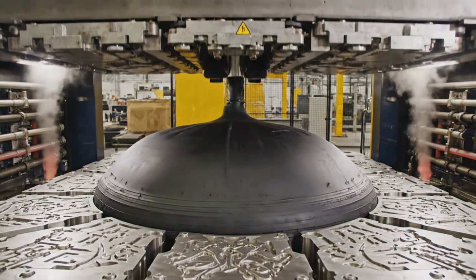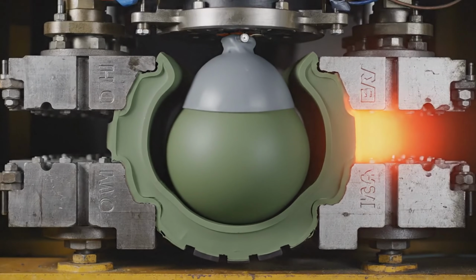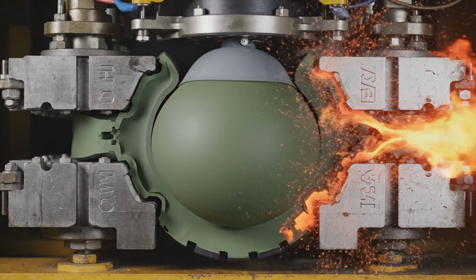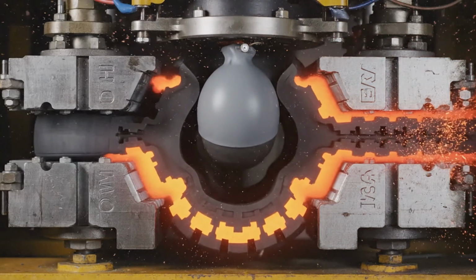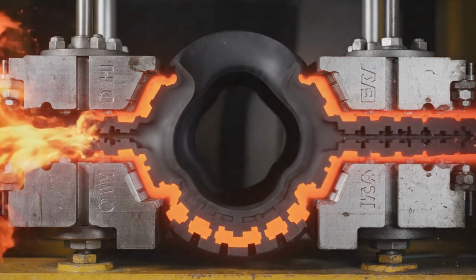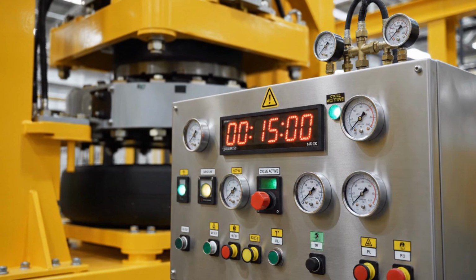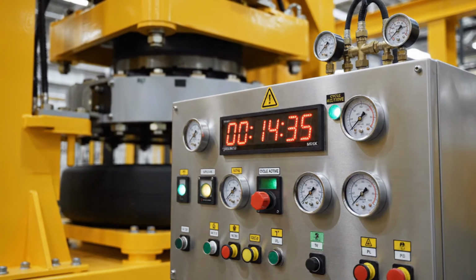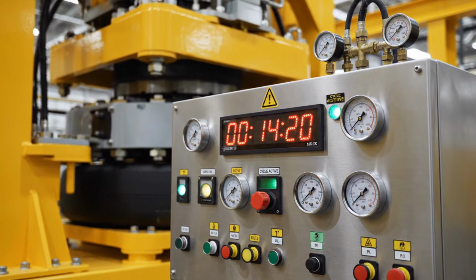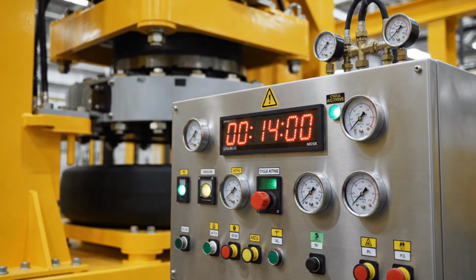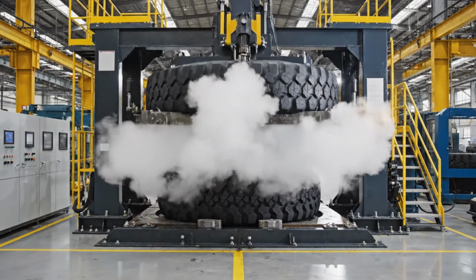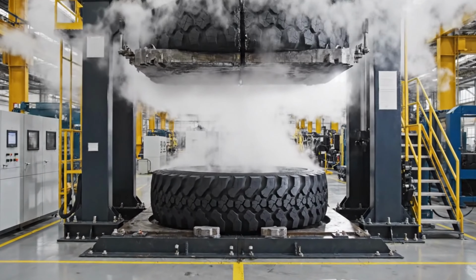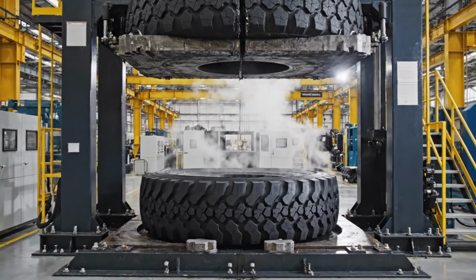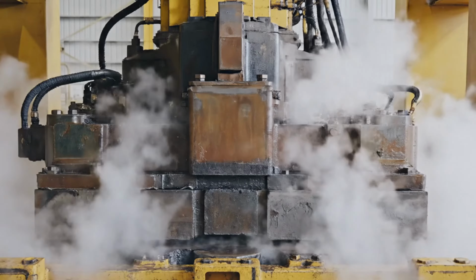Pressures can exceed 300 psi. During curing, the inflated bladder presses the tire outward while the mold compresses inward. This pressure, combined with heat, transforms the rubber. Curing time is precisely controlled, typically 10 to 15 minutes for passenger tires. Longer cycles ensure complete curing. The press opens after the curing cycle completes, releasing steam and revealing the transformed tire.